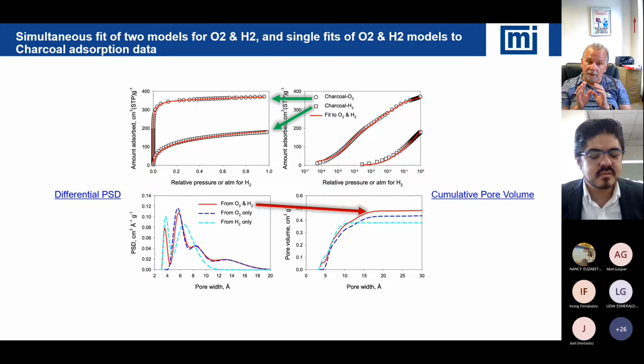From the model standpoint and the calculation standpoint, if the model is not handling things properly at the same sort of isotherm range, a 10 angstrom pore on carbons and a flat surface can appear to be the same. So the calculation process, not the model isotherms, has difficulty differentiating between a pore size and a flat surface for some of the older original models. The more modern models properly take that into consideration. It's the same effect for cylindrical pores, and that occurs at 20 angstroms.